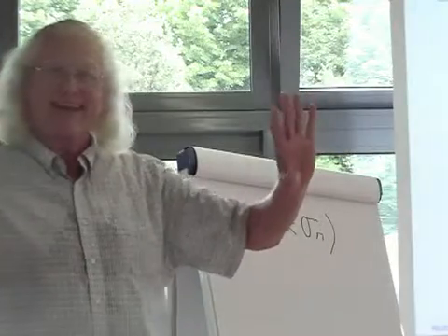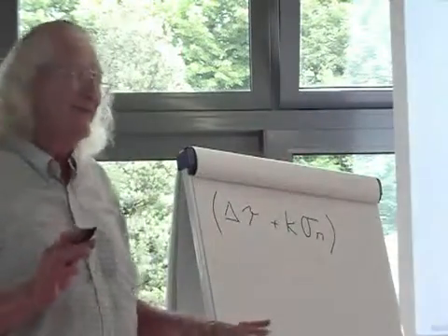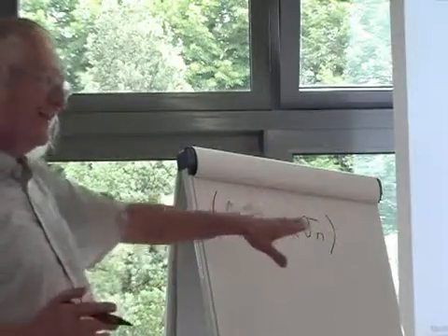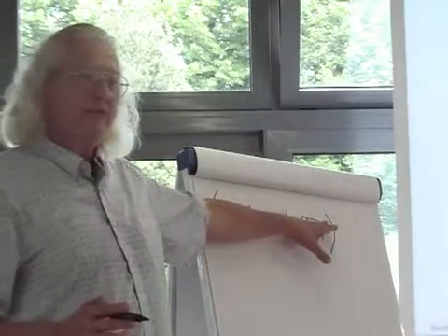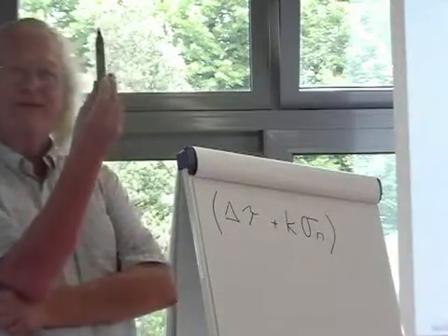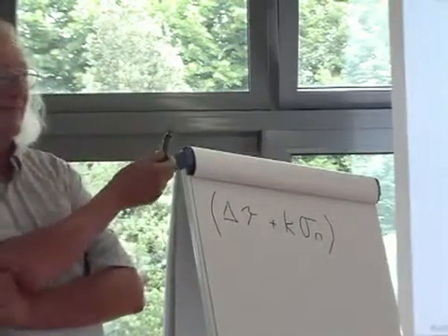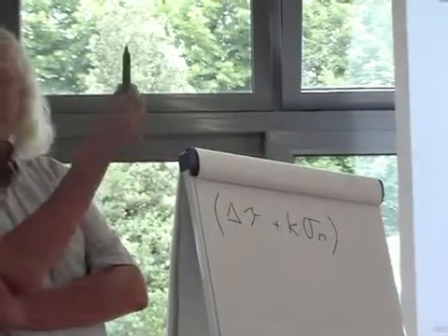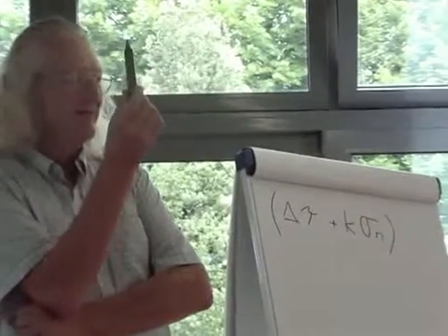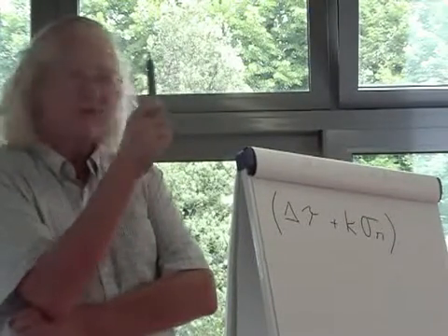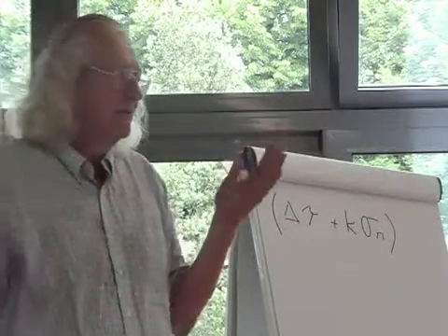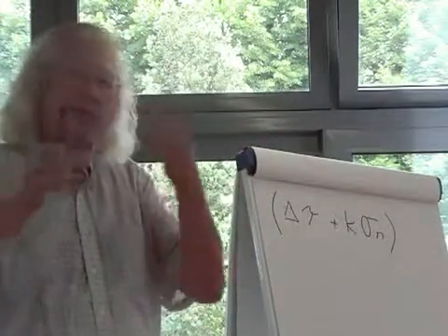Might be some high value, right? Of course, right? So that means there must be fatigue damage under a static stress. That's what the model says, mathematically. There must be fatigue damage even under some static stress. And of course, that's silly. And so it made me think about the structure of the models.